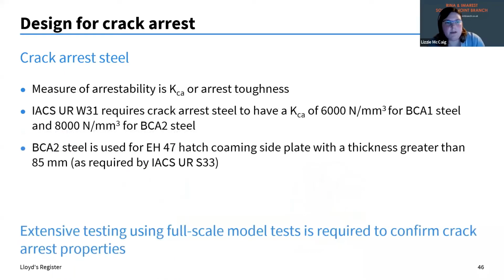Now, the crack arrest steel's measure of arrestability is the KCA, or the arrest toughness. IACS have some requirements about what the toughness of the steel should be, and they have two different levels of toughness. They have BCA1 steel, where the KCA value is 6,000, and BCA2, where the value is 8,000. 8,000 is tougher than 6,000. And then in UR S33, IACS requires that for the hatch coaming side plate, if it's EH47, you've got to use BCA2. So this is an even tougher requirement than you would have for, say, the upper deck, which would be EH36. Now, the issue with crack arrest steel is it's quite expensive. The reason for this is you have to do a lot of testing using full-scale model tests to confirm the crack arrest properties, and that just loads cost onto the material.